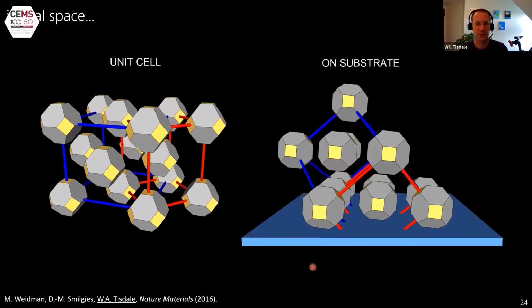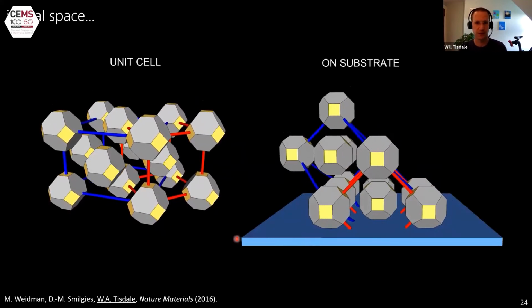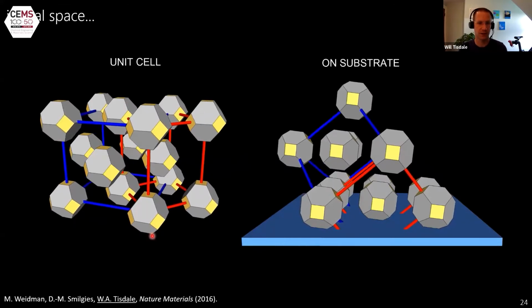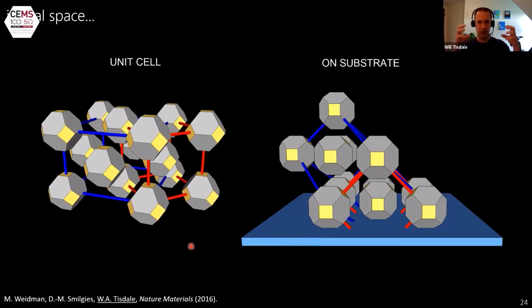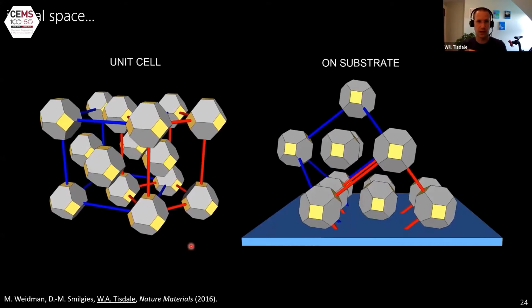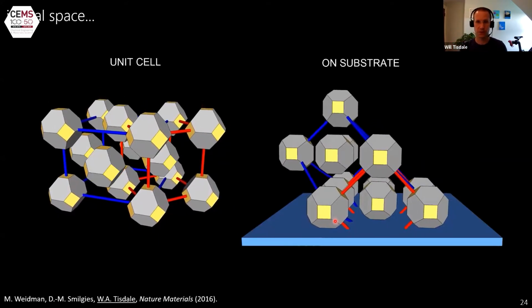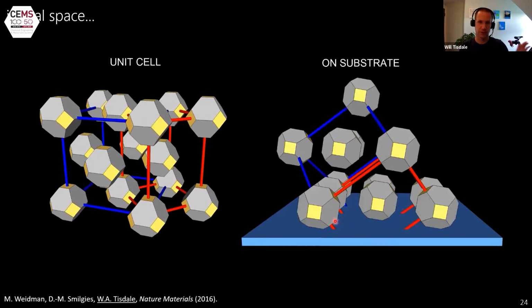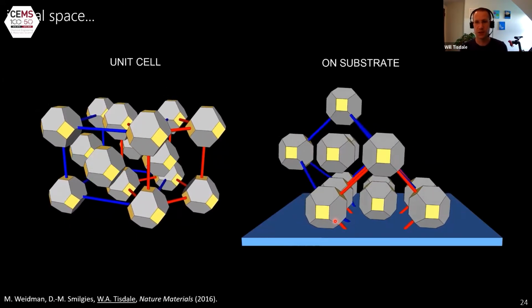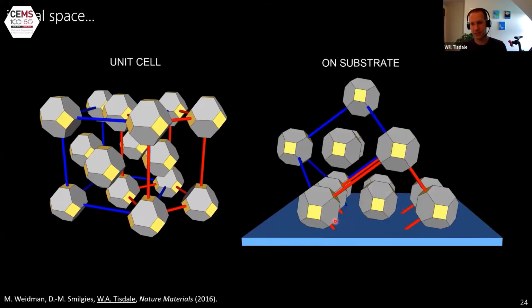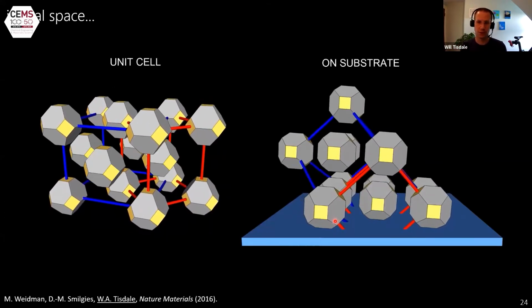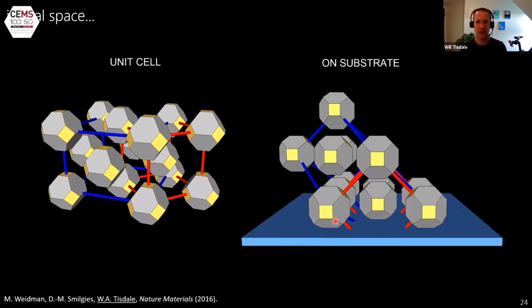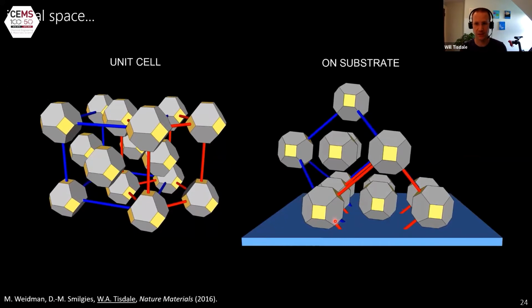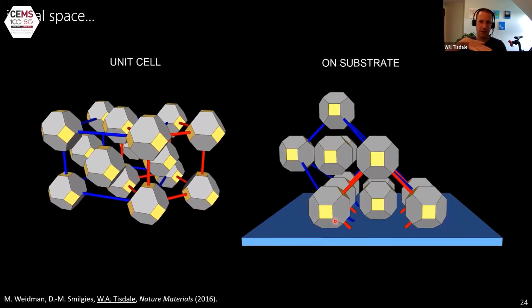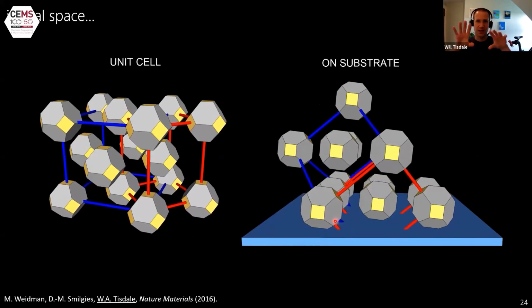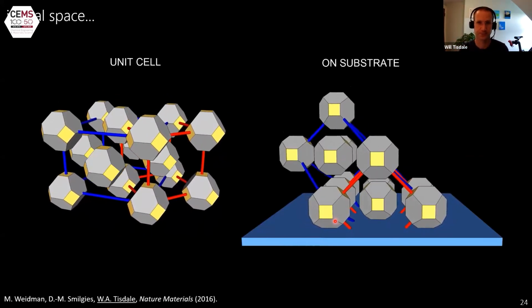Mark was nice enough to make these real space renderings of the crystal. And if you look from the unit cell standpoint, there's actually not a whole lot that's going on. Once they achieve this locked in phase, it's just a uniaxial contraction. But what's interesting is throughout this transition from a BCC structure to an FCC structure, there's a 9.5 degree difference between the 110 close packed plane of the BCC structure and the 111 close packed plane of the FCC structure. And so for the whole superlattice to remain in contact with the substrate, the entire thing has to rotate during this contraction process.